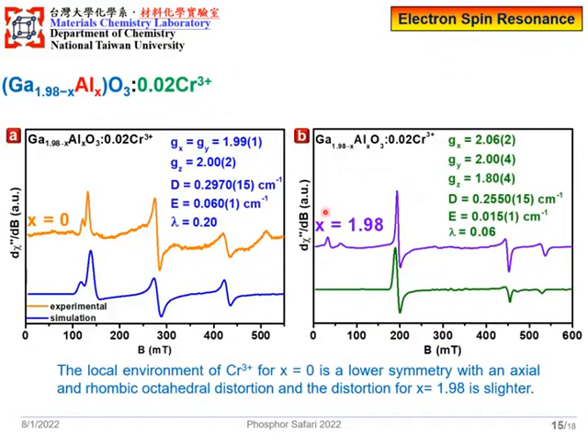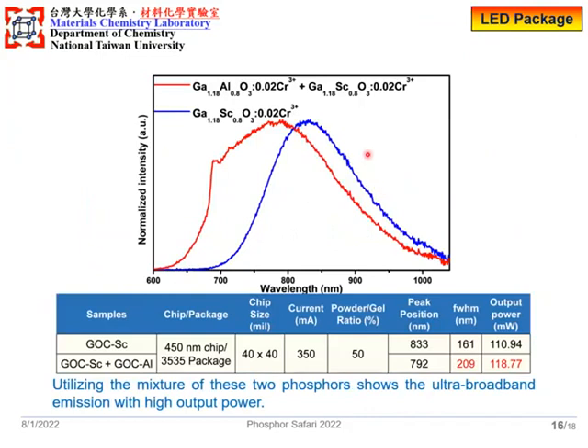To obtain the information of local structure, the electron spin resonance analysis is conducted. The chromium site of gallium oxide shows higher distortion than aluminum oxide. Finally, we fabricate the LED package for the mixture of gallium oxide doping with scandium and aluminum. From this strategy, we can obtain the ultra-broadband emission with high output power.